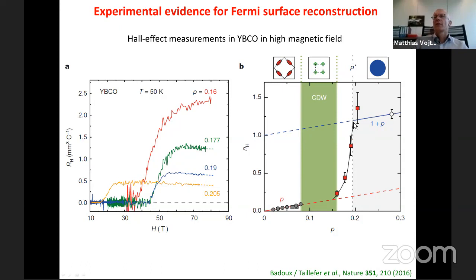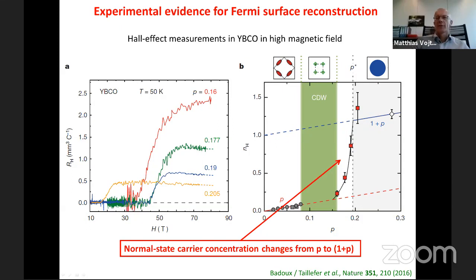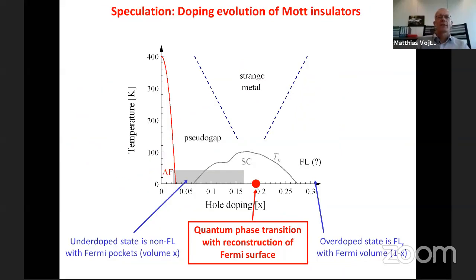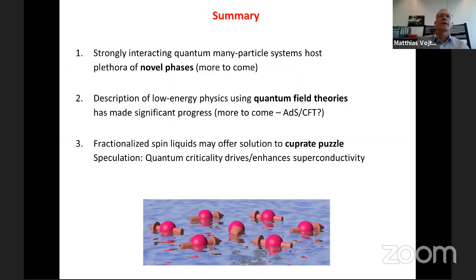And in this regime here, you see actually a relatively sharp crossover from one value to the other, which would involve the transition which I just advocated to you. The normal state carrier concentration, as deduced from this experiment, changes from P to 1 plus P, which supports the idea of a quantum phase transition from a fractionalized Fermi liquid to a conventional Fermi liquid. Okay, with this, I just put up this phase diagram again, and then I am already at my conclusion slide, and I thank you for your attention.